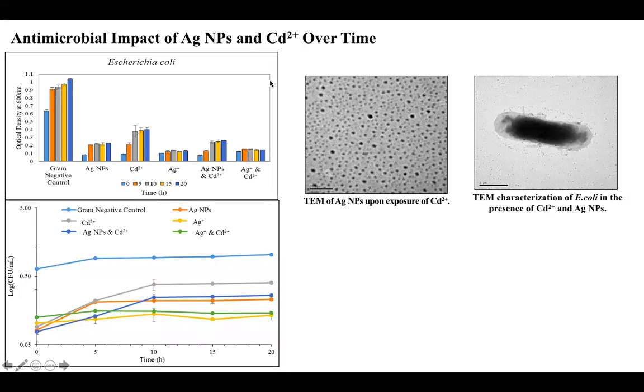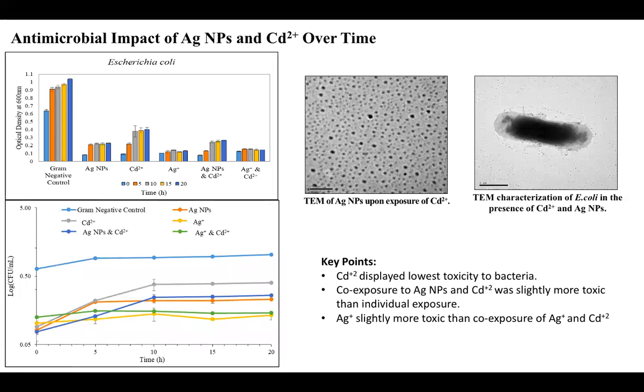All right. And even when we look at cadmium and silver nanoparticles in the presence of E. coli, which is our gram-negative bacteria, again, we see similar data, but cadmium is even less toxic. All of our species are a little bit less toxic than the gram-positive, partially because of the cell wall of our bacterial strains, which we expect to see. Initially, independently, we see a difference in each of our control groups. But as we look at co-exposure, they're similar to those silver nanoparticles or silver ions alone. And there's a slight reduction in our silver nanotoxicity, but not studied enough to see a difference just yet.